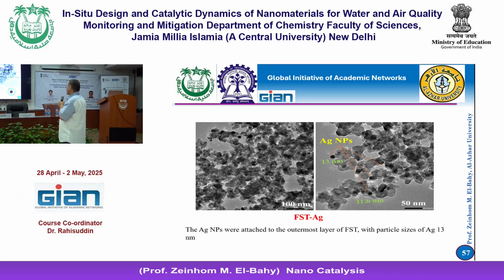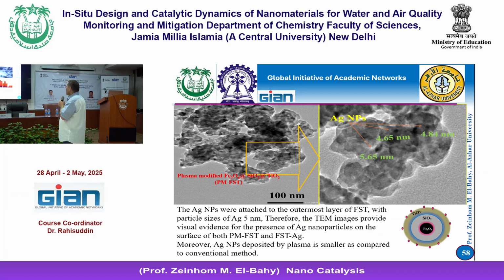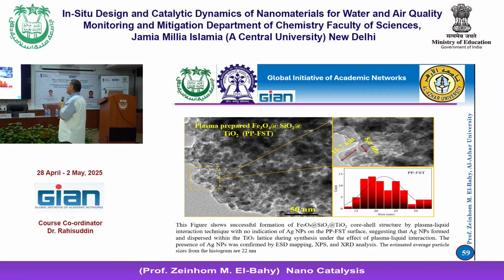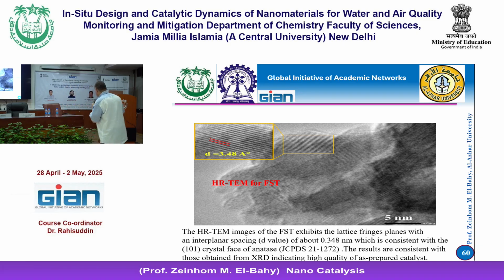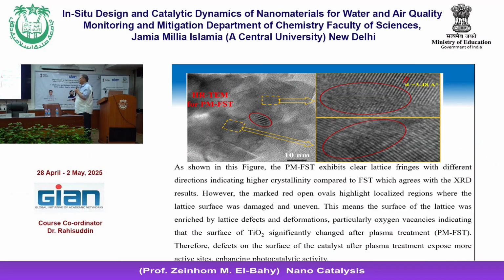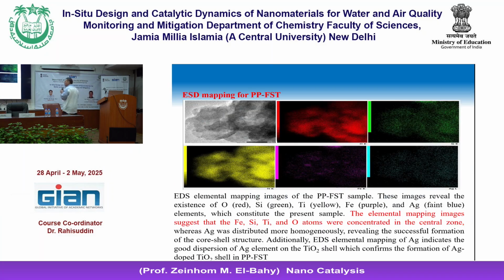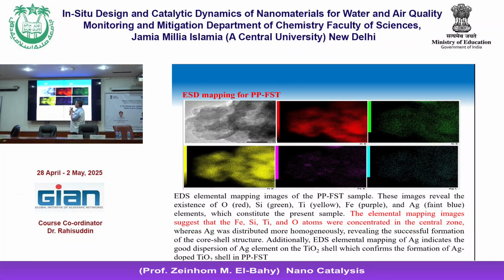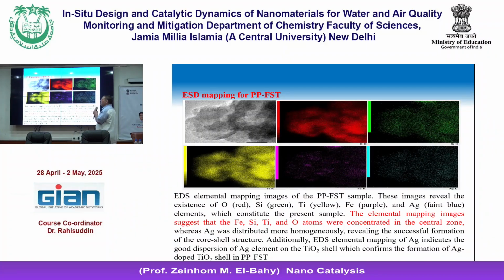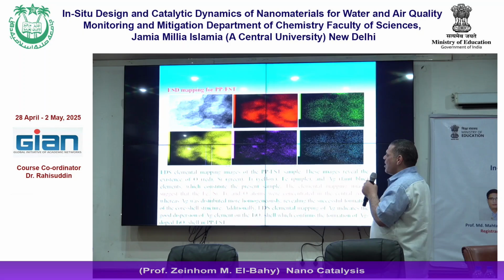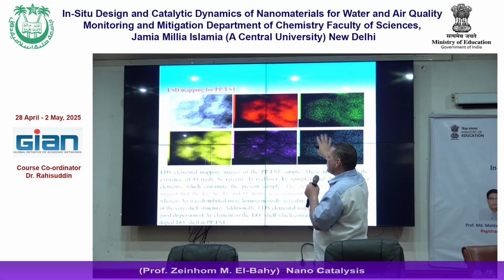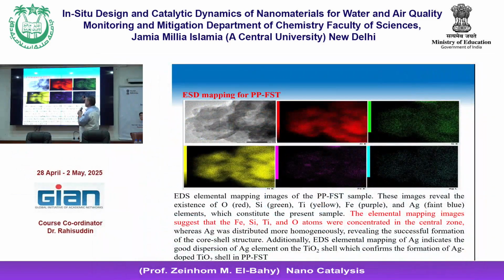And we took these materials and made investigations. This is the TEM images of these materials, and you can see the core-shell, the core inside the shell, as you can see here, and also we got some HRTEM data, like here, and these are other HRTEM data, and after decoration with silver. These black points are silver over FST, which is: F is magnetite, S is silica, T is titania, decorated with silver. And of course, this is the decoration of silver. You can see it here very clearly.